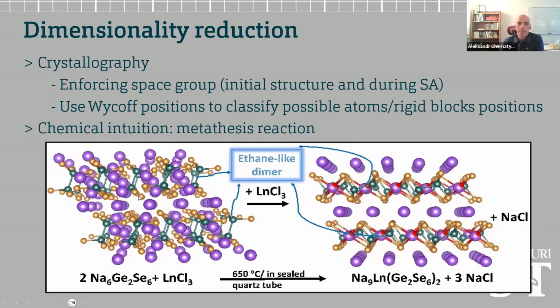And the premise of the metathesis reaction is that this rigid block, this combination of atoms, actually transfers over and stays fixed in the resultant compound when we combine this with, in this case, lanthanum chloride. And we can see that this rigid block stays intact. That does not change. And we do change the elements which we have inside. So we now have lanthanum contributing to the system, and it's now a part. In this particular case, there's going to be some disorder here. It's going to be partial occupancy. So that particular combination will cause trouble.